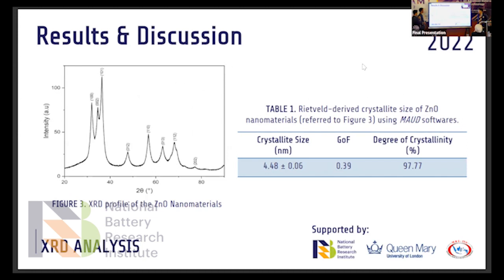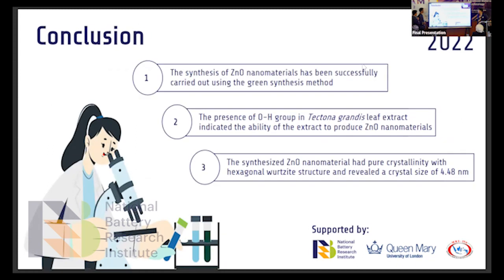Next, figure 3 shows the XRD profile of the ZnO nanomaterials. It shows the formation of pure hexagonal wurtzite structure zinc oxide with 4.48 plus minus 0.06 nanometer crystallite size. From this presentation, we conclude that one, the synthesis of the nanomaterials has been successfully carried out using the green synthesis method, two, the presence of OH group in Tectona grandis leaf extract indicates the ability of the extract to produce the nanomaterials, and three, the synthesized nanomaterials had pure crystallinity with hexagonal wurtzite structure and revealed a crystal size of 4.48 nanometer.